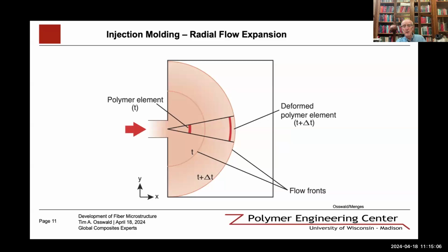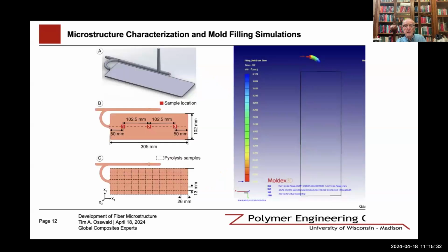There is, of course, also radial flow expansion in the central core of the part. So there the fibers will get oriented perpendicular to the direction of flow. So typically you will have orientation perpendicular to the flow in the central core of an injection molded part, and then you would have orientation in the direction of flow in the outer skin. So if we can, for example, look at an example, the part here.